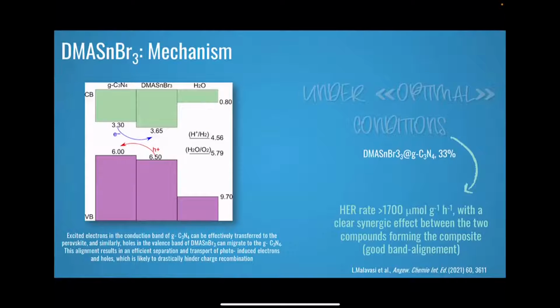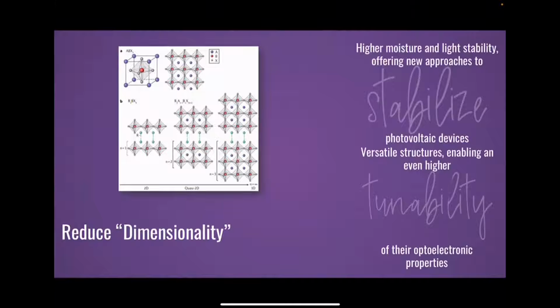It was a demonstration that you can play with them, but of course we are now moving toward more stable systems. In this case, the idea is to reduce the dimensionality of the perovskites and play with two-dimensional perovskites. Here you see the three-dimensional perovskite as I showed you before, like dimethylammonium tin tribromide. In the two-dimensional perovskites, you have a layer of inorganic framework of octahedra, for example, tin bromide 6, and this layer of octahedra is separated by an organic spacer, which can be even very big. These perovskites are more stable towards water, for example, because here you can put very huge organic cations, and again, you can very easily tune their optical properties by chemical substitution.